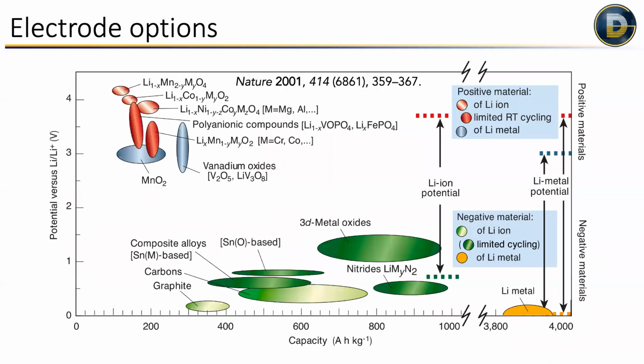So then when we're making a battery, we have to select two materials, one for the negative electrode. So those materials are shown here on the bottom. Those are at low potentials versus this lithium plus, which is basically where a lithium ion will become a lithium metal. It'll accept its electron back at 0 volts. And then your positive electrode materials up here include lots of these mixed metal oxides. So it's like lithium and manganese and maybe nickel and oxygen.